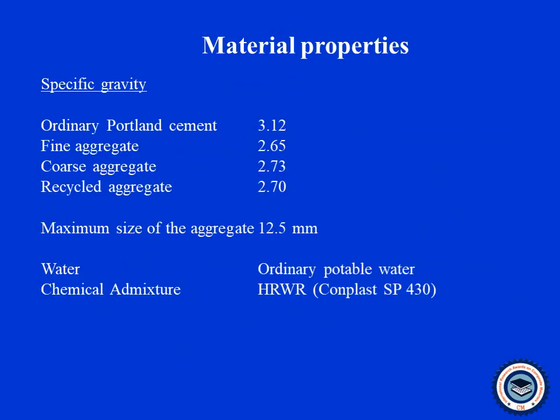So these are the material properties used for this research work. Ordinary Portland cement was used, and the specific gravity of the cement is 3.12, and ordinary fine aggregates obtained from the rivers, and coarse recycled aggregate having 2.7 specific gravity is used for this work. The recycled aggregates are retrieved from a demolished building of age more than 60 years. The maximum size of the aggregate is 12.5 mm. We reduce the water cement ratio by using the chemical admixture Conplast SP430.